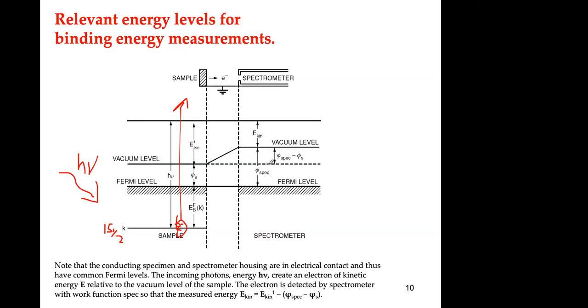What happens here is that the work function for the spectrometer and the sample might be different, and you have to correct for that. If you just analyze the kinetic energy without correcting, as you see here, the work function is larger, so the kinetic energy that you measure at the end will be smaller than the real one, and the spectrum will be at another binding energy. So you need to use a standard. Usually they use gold 4f electrons. They also use carbon: since most of the samples you analyze are exposed to air, they will have a very small film of carbon on the surface, and it's usually used as a reference, the carbon 1s.